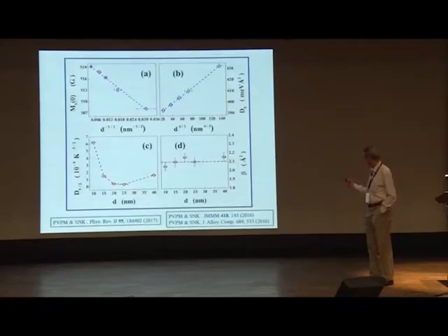And you see now these are the fit parameters as a function of thickness. You see that the spontaneous magnetization at absolute zero and spin wave stiffness at absolute zero scale with the average crystallite size according to these power laws. So that would tell you that the average crystallite size is a relevant scale for spontaneous magnetization in these systems.